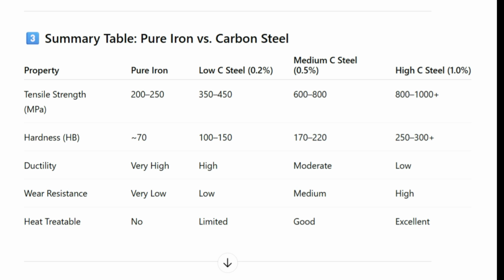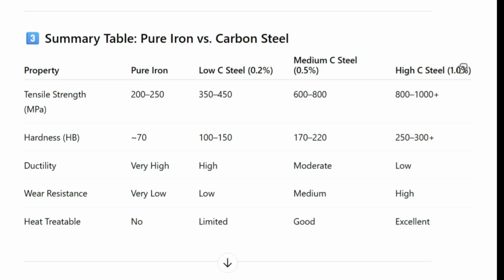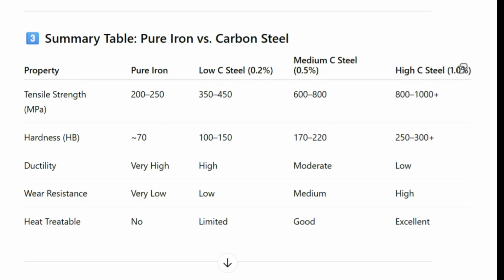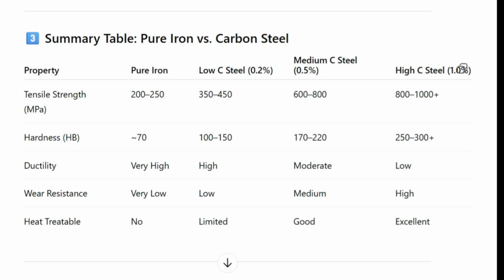And high carbon steel, which is 1% or above, gives 800 to 1000 MPa. It's a big tensile strength. But see how the hardness is impacted. Brinell hardness is 100 to 150 for low carbon, still with 0.2%. Now, with medium carbon 0.5, the hardness goes to 170 to 220 Brinell hardness number. And for high carbon, 250 to 300. So it's becoming very hard.